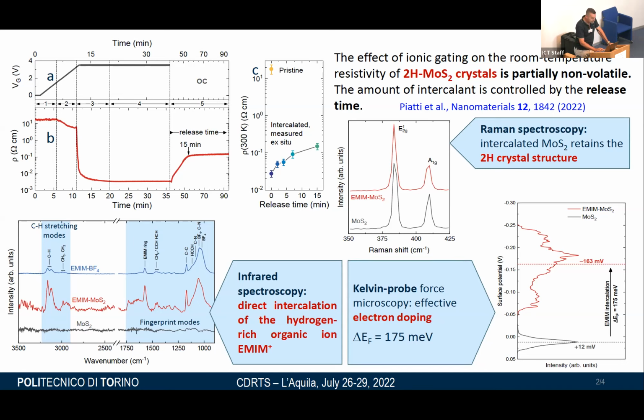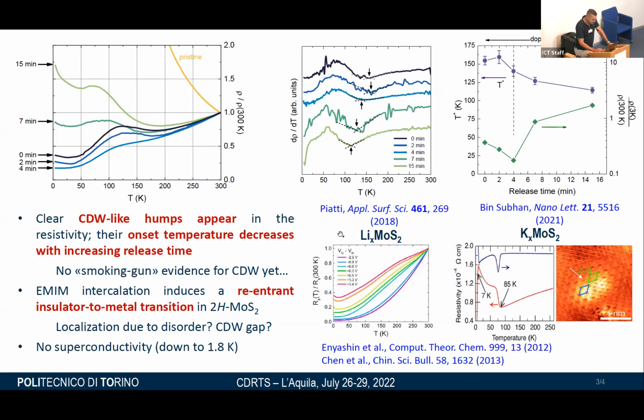And what happens to the resistivity, to transport properties? Well, the pristine sample is, of course, an insulator. And by choosing the release time, we can go to higher and higher dopings. So we go from smaller doping to increasing doping, and the most doped sample is then the black one, okay?